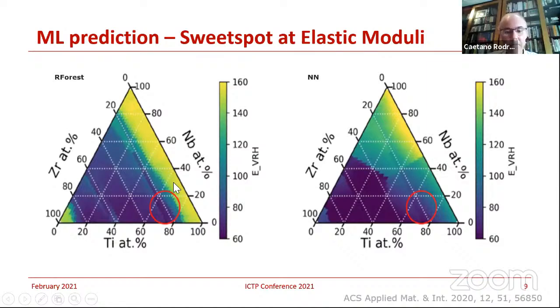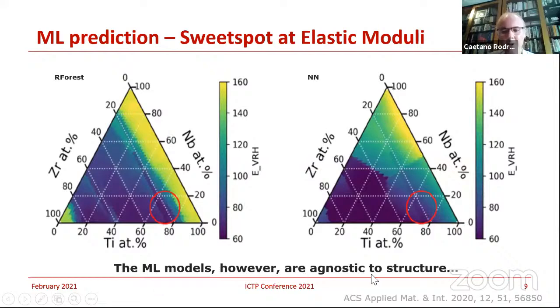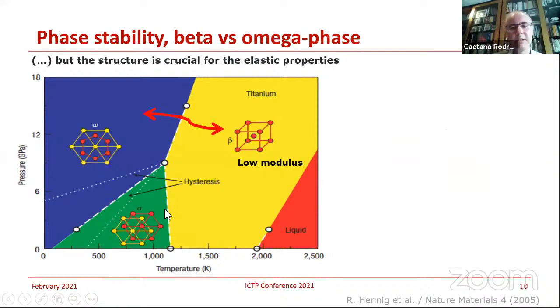This was the map for us to look for those compositions in order to see if you can end up with a material with a low elastic moduli that can be applied in bio implants and bio applications. Now, however, I have to remind you that these machine learning predictions are only based on composition, meaning that they are agnostic to the structure. So this is where you have to use first principle calculations, for instance, in order to understand and validate if those compositions are really stable, and also can be used as a good material for bio implants and bio structures. So this is more or less what you have done. For the sweet spot in this composition, you then look, based on first principle calculations, at the phase diagram.